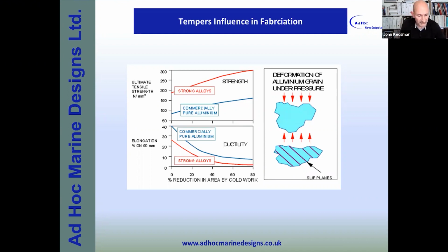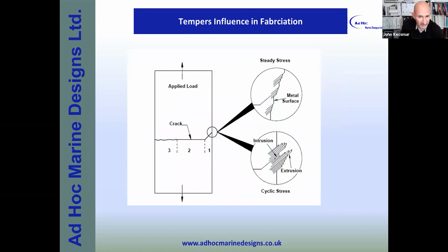Well, the reason why this is quite important is it's actually very, very familiar. And why is that? Because when we look at how fatigue starts, it's the very same mechanism. The initiation of a crack involves the localized movement of dislocations along the very same slip planes that you're using to mechanically work the material. So the same slip planes that you're using for strain hardening are also the very same that are used in the mechanism, if you like, of crack initiation.